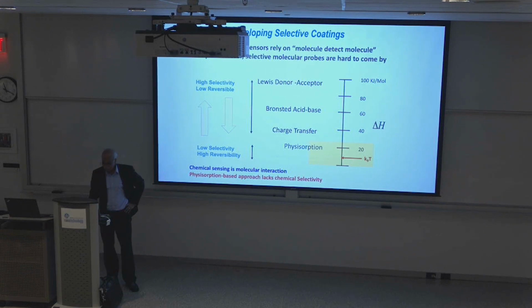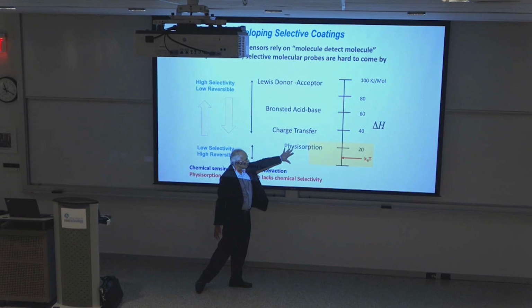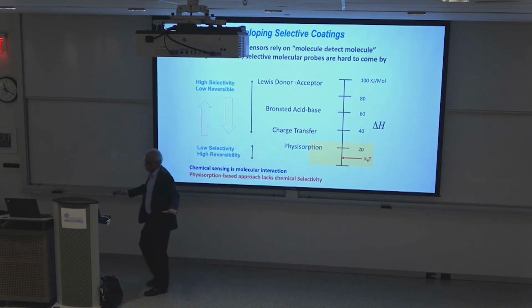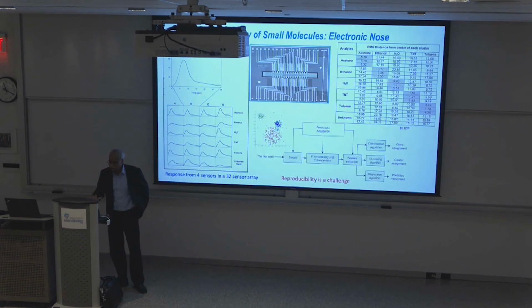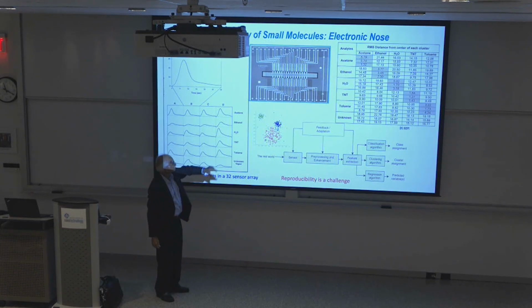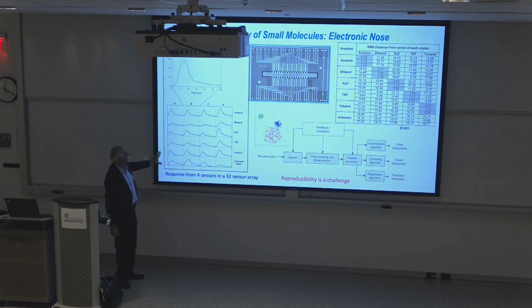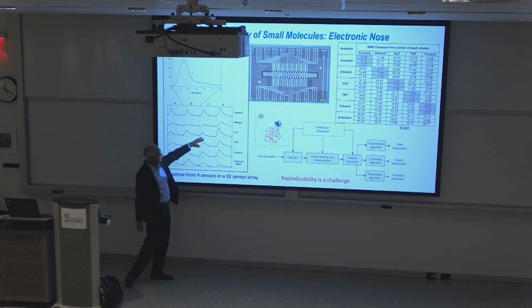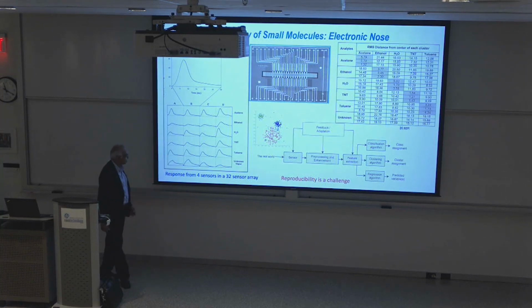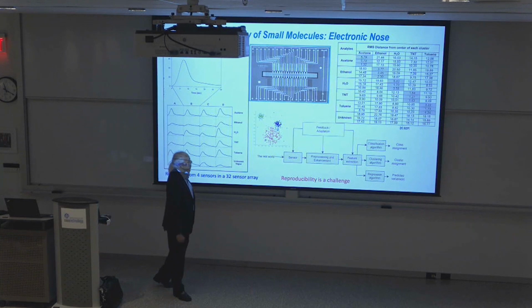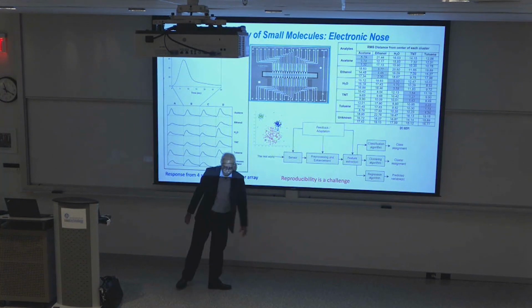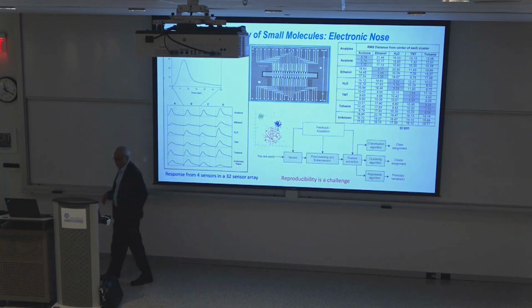So maybe we thought, okay, we can use the idea that we use hydrogen bonding and make an array and then use machine learning. So this is the array again, coated with different things, and only 4 cantilevers are shown here, A, B, C, D, trained with acetone, ethanol, water, TNT, and then an unknown vapor. And remember that there are 32 of them, all exposed at the same time. And then we send it to some machine learning type technique, and this also fails. After some time, it doesn't work anymore